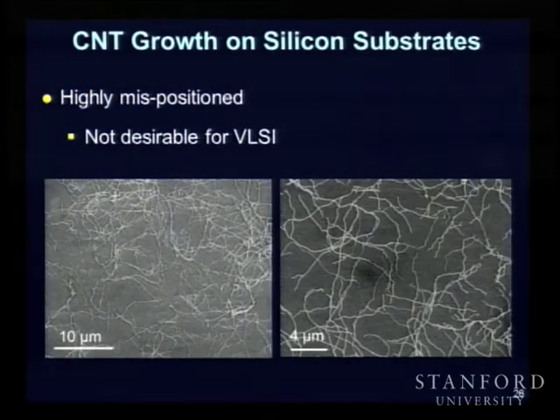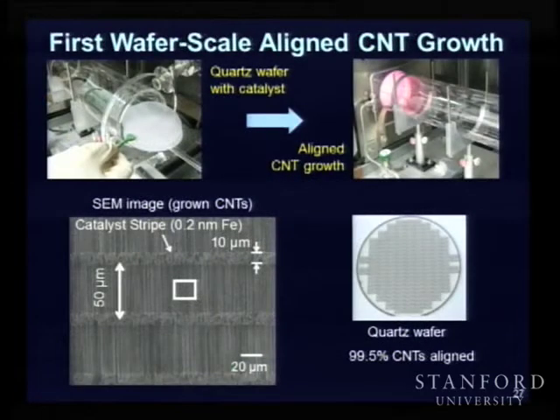Okay, so I have shown a lot of theoretical stuff. Let's look at some pictures to make sure that these are really real. If you grow carbon nanotubes on silicon substrates, you get what I call a bowl of noodles, right? Versus if you grow carbon nanotubes on a quartz substrate. And by the way, our group has been able to demonstrate the first wafer scale aligned carbon nanotube growth, and you will see all these equipments in the CIS building right next door, and we'll be happy to give you a tour if you're interested.